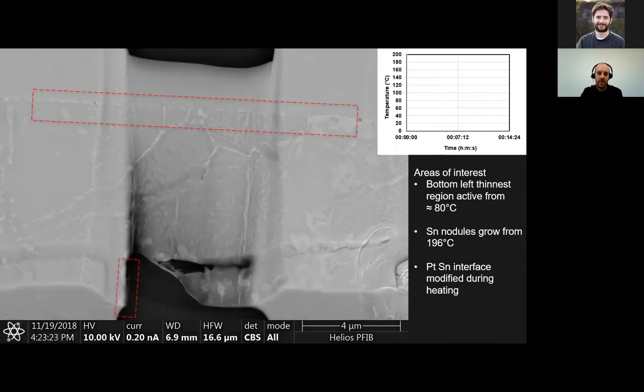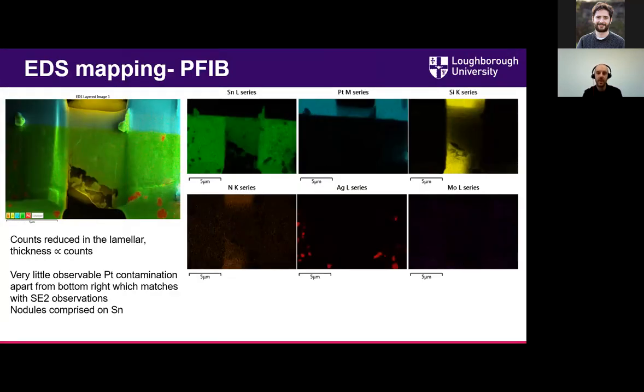We could do a little bit of EDS on this, and we identified that these nodules, as I said, were tin-based. This is a similar process to, I think, the research Dan does on tin whiskers. So we're essentially watching tin whiskers form from the platinum-tin interface.